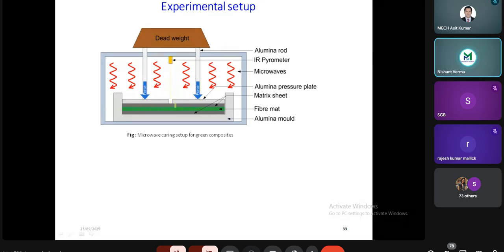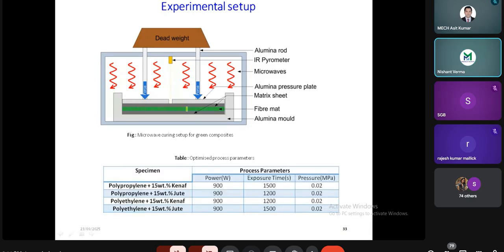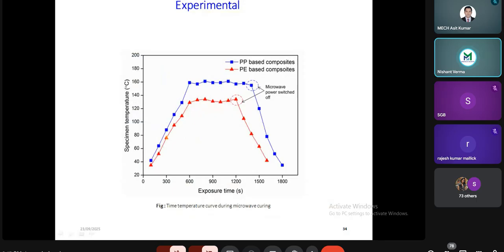The whole mold is covered, and the fiber mat as well as the matrix can be visible in the slides. As I already explained, if the fiber is microwave absorbing, it would interact with the microwave rapidly compared to the matrix material, and it would start heating first. So these are the exposure time and pressure, and we can see the temperature-time curve for the same, for the PP based composite and PE based composite. At this stage we are switching off the microwave power, and up to this region we have heated the sandwich.